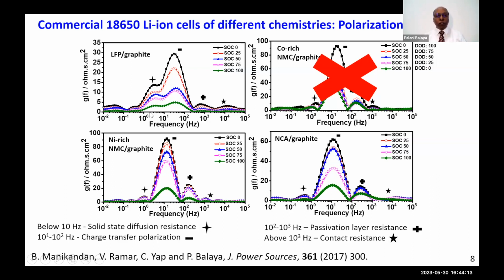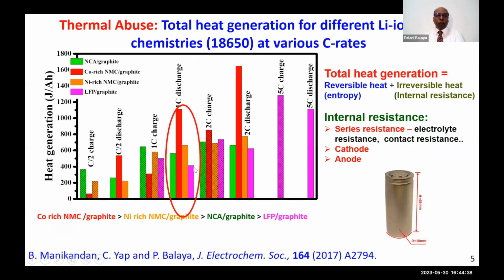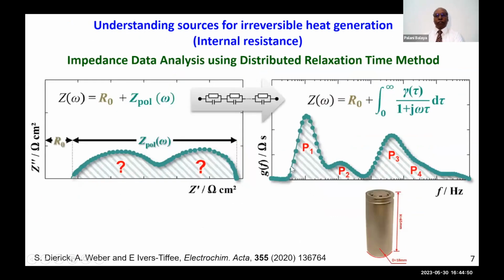The next one is the lithium diffusion within LFP. You can see here, this is the next contribution. This is the SEI, this is the contact and electrolyte. So you can see here the big bottleneck for the internal resistance. In other words, the heat generation is due to the charge transfer that is happening in the cathode or positive electrode. And interestingly, if you look at the values for the LFP chemistry, you see that it is lower as compared to oxide chemistries. That explains why the LFP has the lowest heat generation. So I'm just ignoring reversible heat at the moment. But if I take into account only the irreversible heat loss, you can see that this is closely related to the internal resistance.